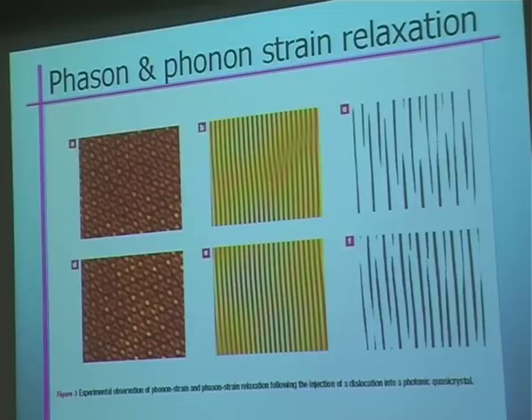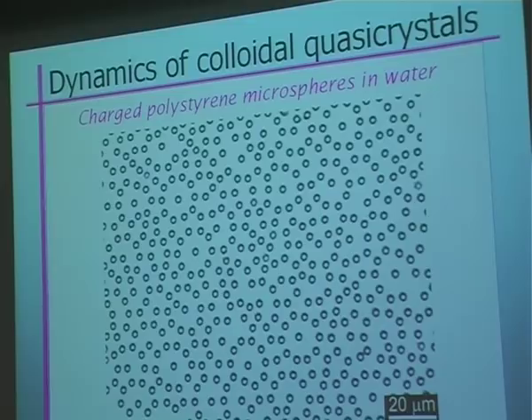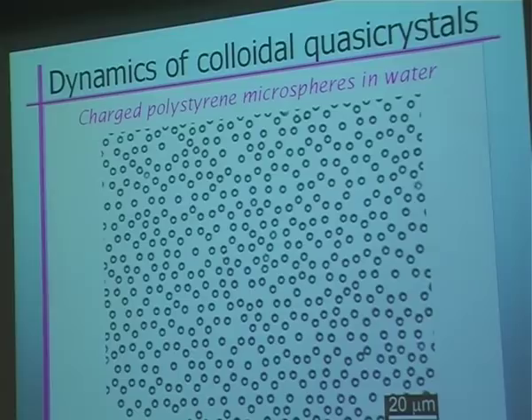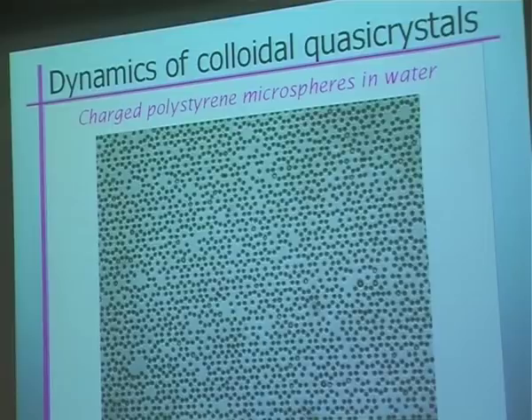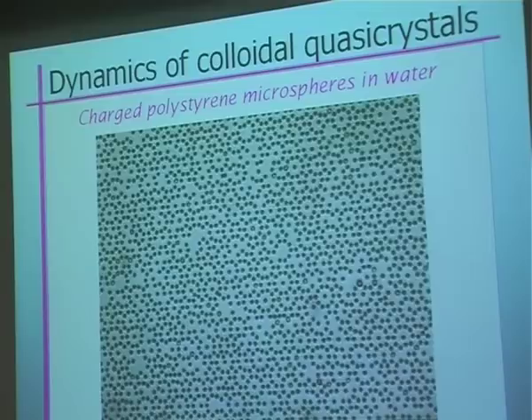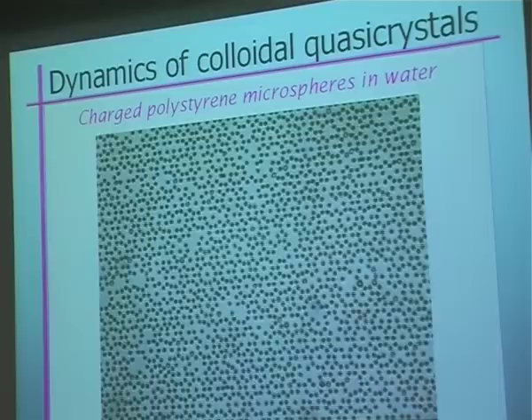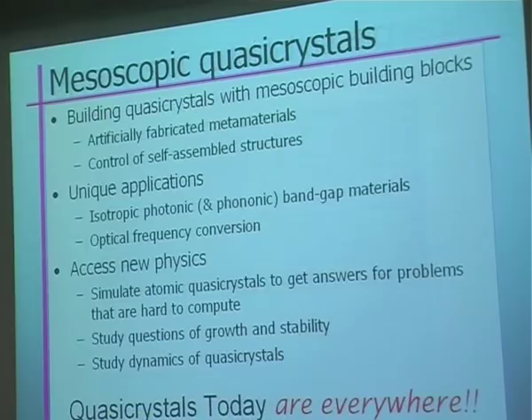The last topic is ongoing research with my student Liron and Clemens Bechinger's lab on the colloidal system. Order is induced by an external potential, but these little particles are in water at real temperature, so they jiggle as overdamped Brownian particles. A movie of these particles shows not only fluctuations around local equilibrium positions, but also particles jumping between positions every once in a while. We clearly see a combination of phonon fluctuations and phason fluctuations, and we intend to analyze these quantitatively.